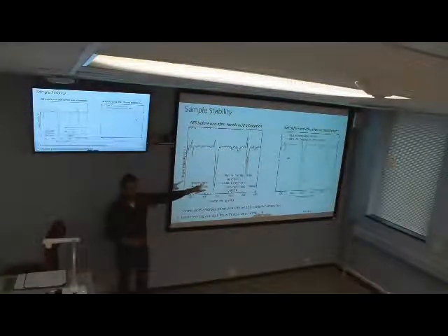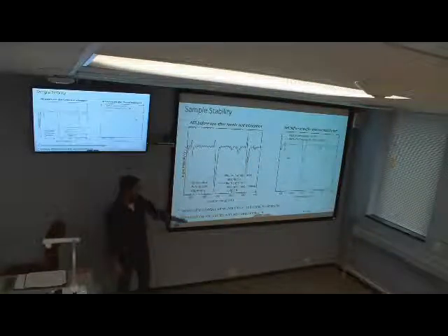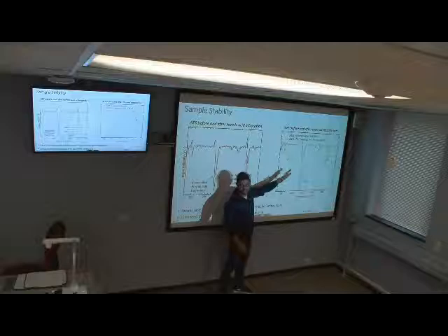Okay, yeah. But you cannot really quantify it, right? By how much? It's just qualitatively seeing the AES spectra, as I was telling. If we have the same spectra before and after the formic acid adsorption experiment, with a thermal ramp of up to 750 Kelvin, we have a certain amount of perovskite left over because we have a similar peak pattern here. But here the peak pattern is quite different. As you can see from the AES, it's a similar thermal ramp, but after that thermal ramp, the film seems to be completely destroyed.